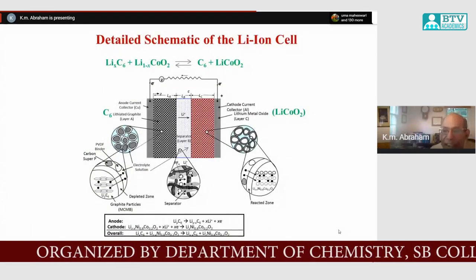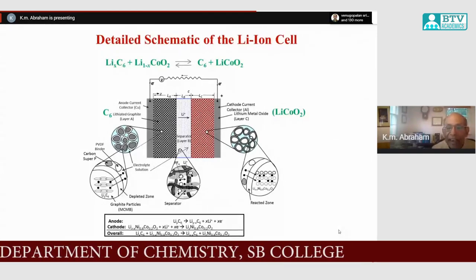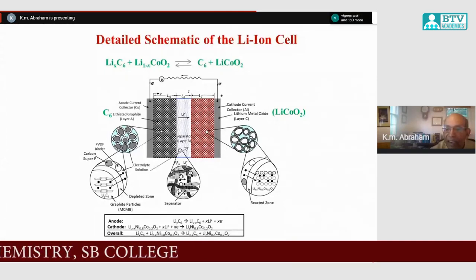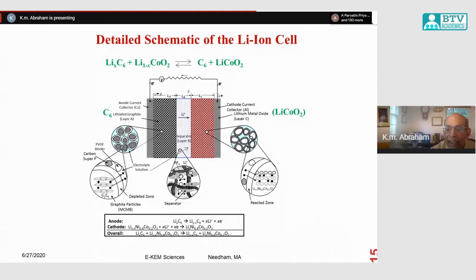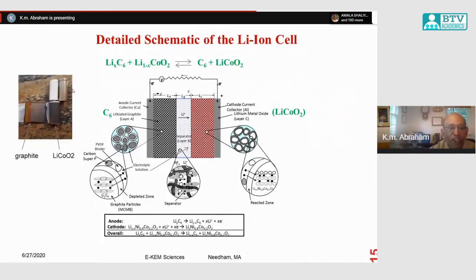So this is the detailed schematic of a lithium-ion cell. It's a pretty complicated device where you take your cobalt oxide as a very fine, micron-size powder and bond it onto a current collector, and the graphite is also taken as a fine powder and bonded onto a copper current collector. You make long sheets of this, about a foot long, in this particular original battery which Sony came out with, called an 18650 cell, which is a particular size: 18 millimeters diameter and 65 millimeters length. So this is the original Sony battery design.